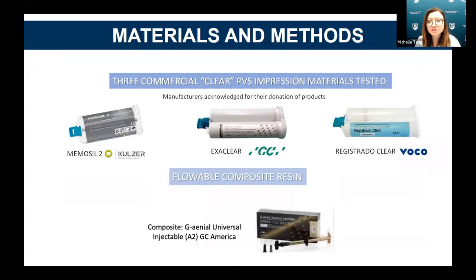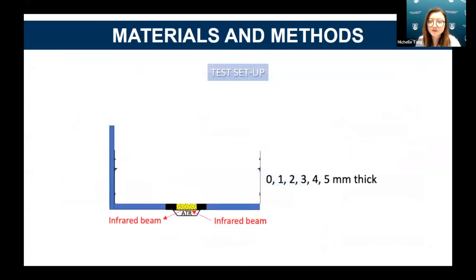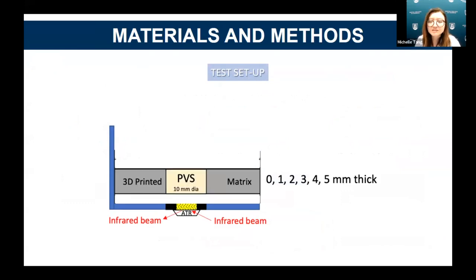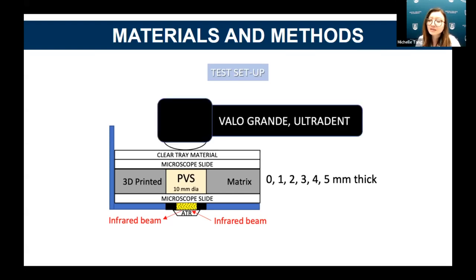GC's G-aenial Universal Injectable Composite in the shade A2 was also used. In our setup, a 3D printed jig was utilized that would contain a 2 millimeter thick flowable, as shown in yellow. Pre-made PVS matrix of varying thicknesses was placed on top, sandwiched in between two clean microscope slides to preserve a bubble-free environment. A clear tray material was then placed on top, and the Ultradent Valo Grande curing light was shone from the top, allowing light to penetrate through the layers.